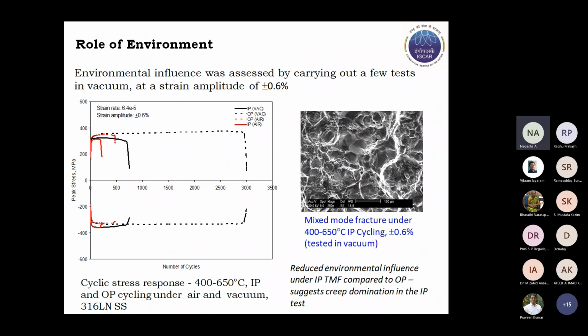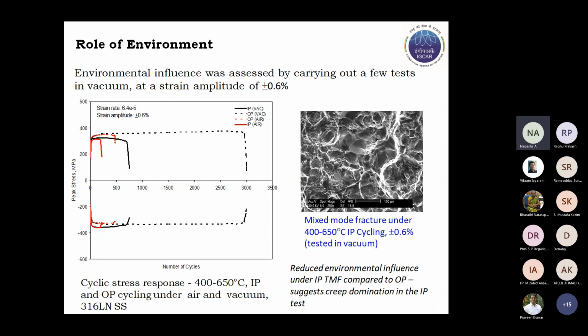As we can see here, this red solid line shows the in-phase cycling in air, and what we can say from this is that the environmental influence is much reduced under IP-TMF in comparison with OP-TMF. This suggests creep domination in IP tests, because the life difference is not much in air compared to what is happening in vacuum. Because IP is largely governed by creep deformation, in vacuum there is not much of a difference compared to air, as against the case with OP-TMF, wherein a large difference is seen.